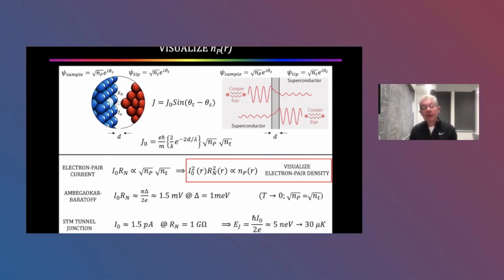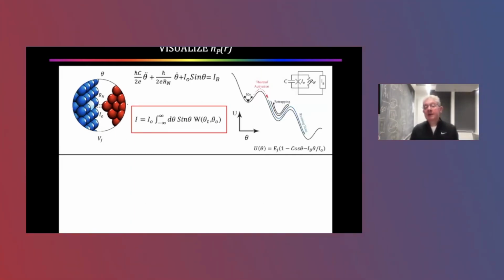However, you really can't do this as shown on the screen here. The reason is that the junction resistance for STM is enormous. So that means the Josephson critical current is tiny. It's a few picoamps. And so the Josephson energy is equivalent to a temperature in the microkelvin range. You need a microkelvin STM. No one has succeeded in doing this. Luckily for us, Bob Dynes identified a solution when he pioneered this technique.